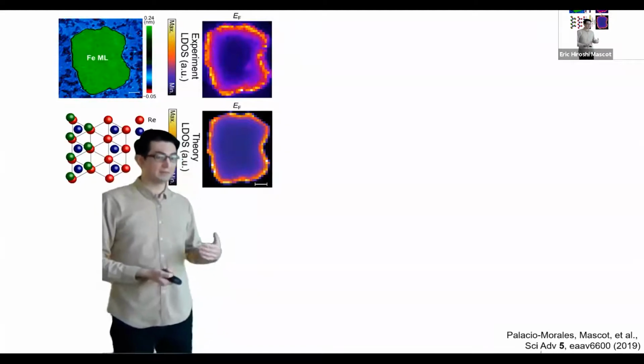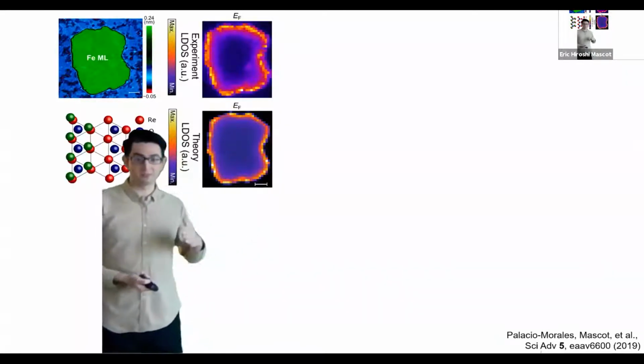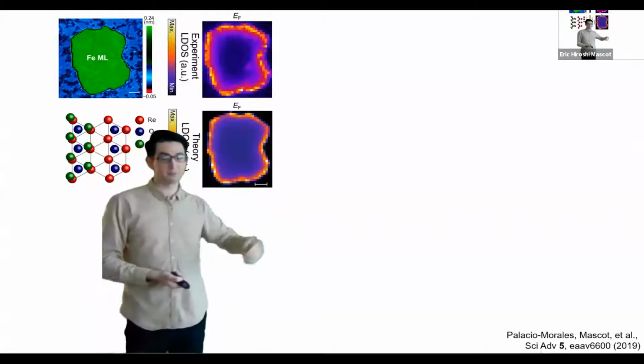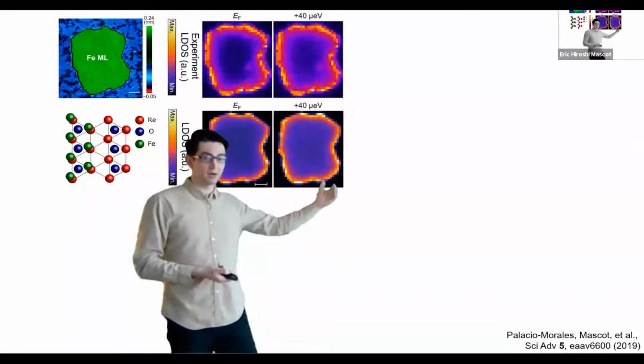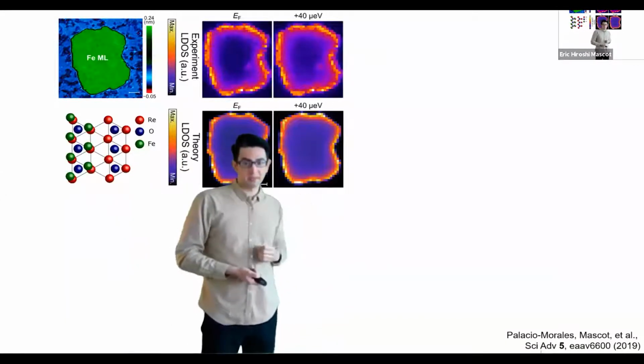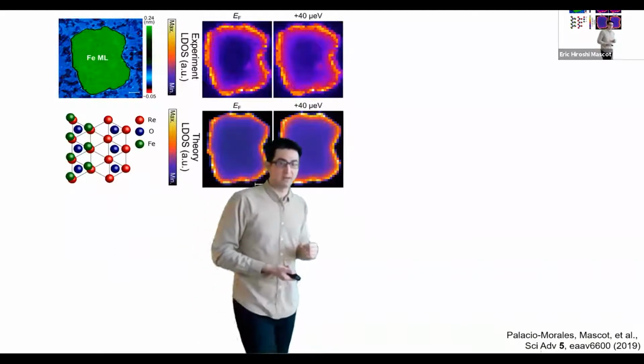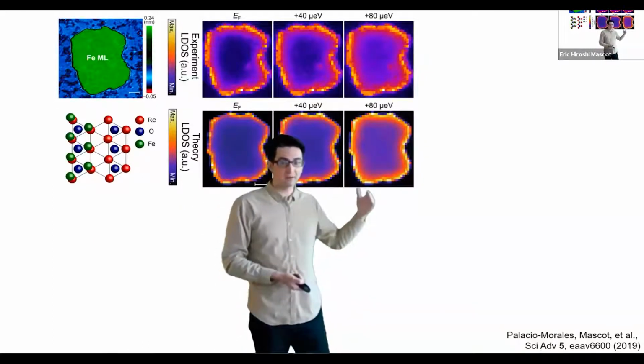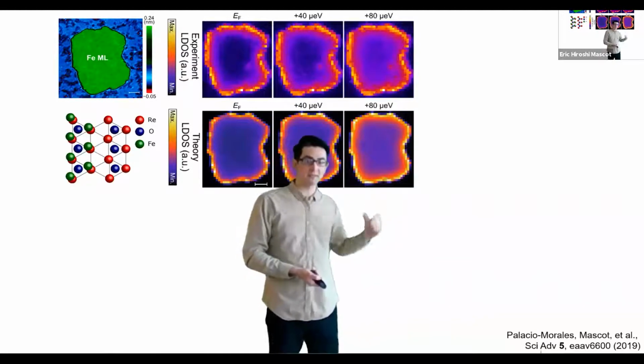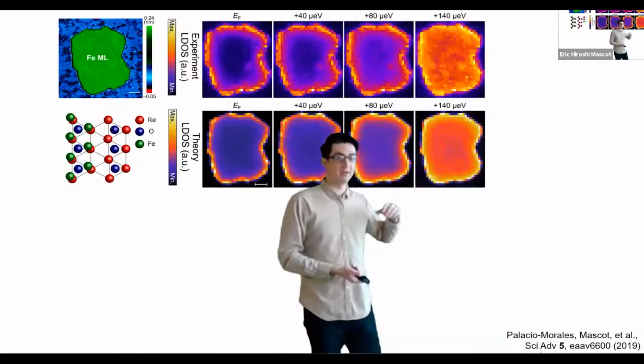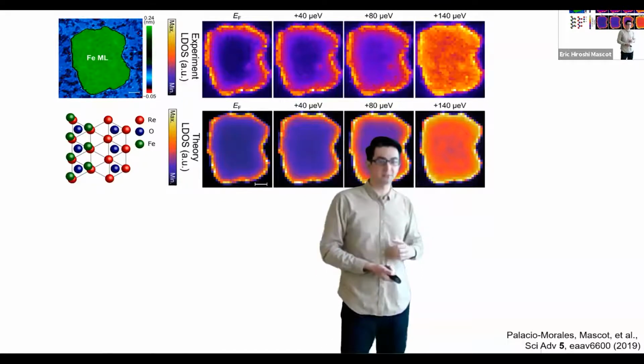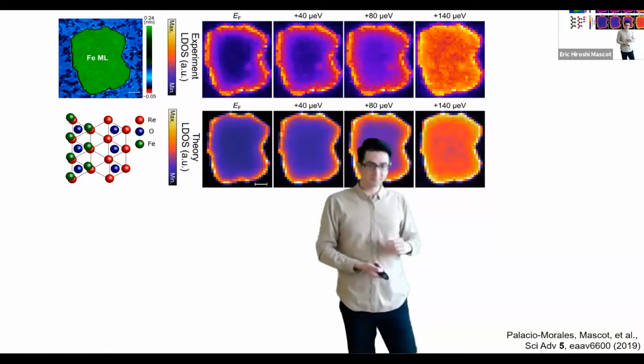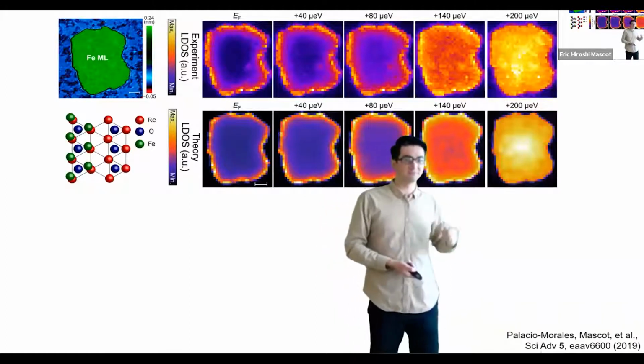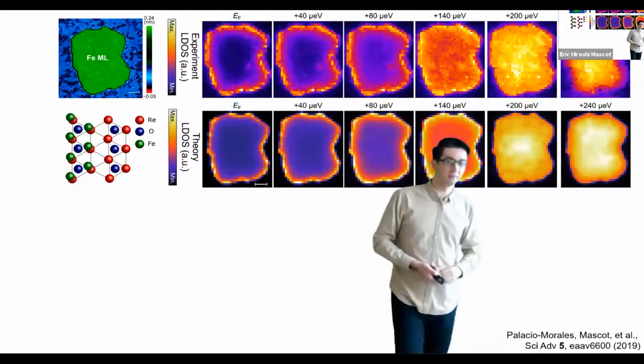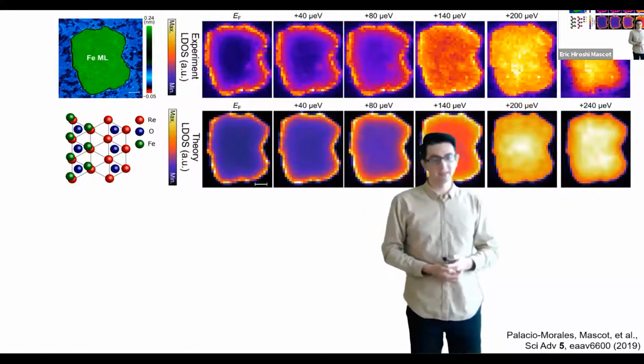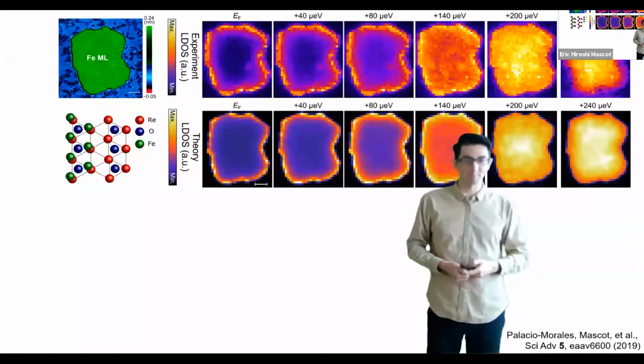And if it's a topological edge, we should see it cross the superconducting gap. So as we go up in energy in both theory and experiment, we see this edge mode. And as we go higher in energy, this localization length starts getting longer until we start getting close to the superconducting coherence peak, after which we only have bulk states. And so now all we see are bulk states inside of the island once we get to the superconducting gap.